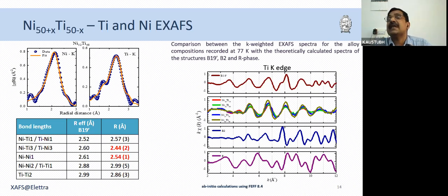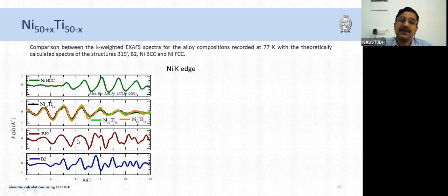And so we thought, okay, we should do the same exercise for nickel. And when we did that for nickel, you can see that the nickel experimental data, especially above 7 angstrom inverse, does not replicate the EXAFS of B19 prime, or the oscillations in B19 prime. And then we thought probably this is because when we take a non-stoichiometric alloy, we create nickel-nickel nearest neighbor pairs, and therefore we should try and see if these oscillations are replicated by nickel-nickel correlation. So we took the metastable body-centered cubic structure of nickel, and we calculated EXAFS for that, and you can see that there is some sort of a resemblance with the BCC phase of nickel.